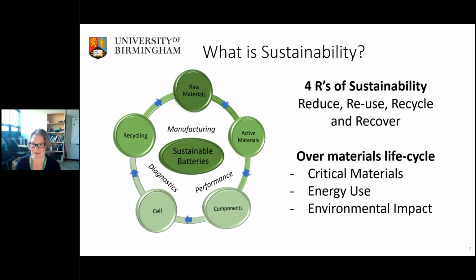So what is this sustainability? Now, I've talked about the criticality of materials, and what can we do here? Well, we can reduce the quantity of critical materials that we use. So, for example, cobalt is being replaced with nickel, which is less critical. Or we can substitute. So we can substitute the lithium, for example, for sodium. And we can start looking at creating a circular economy for these minerals and metals as well, so that they're not shipped back to China to reprocess so that we buy it back again, but we start to reprocess, recover, and then remanufacture within the same geographical areas. The other things that we need to consider, though, is that energy usage. How much energy is used to do that processing and those manufacturing, and what kind of environmental impact does that have?